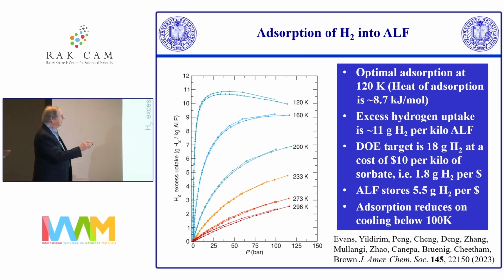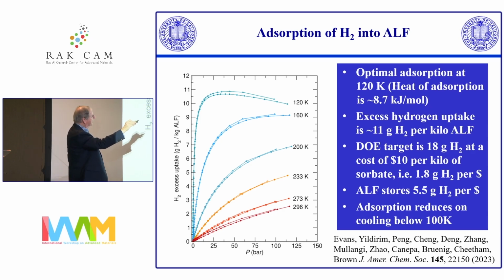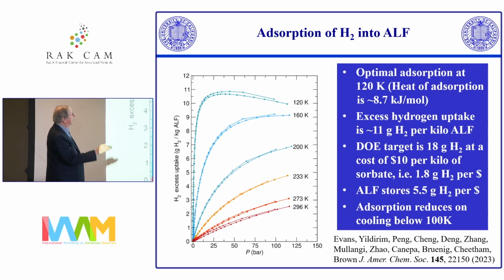And so this is the performance of our material. Optimally, it works at about 120 K. And as you increase the temperature, you can see to 160, 200, 233, and so on. It goes down. That's a sort of normal thermodynamics. But under these conditions, and at quite low pressures, this is not 350 atmospheres of hydrogen. This is, say, 15 to 20 here. And the heat of adsorption is nearly 9 kilojoules per mole. Our hydrogen uptake is about 11 grams.